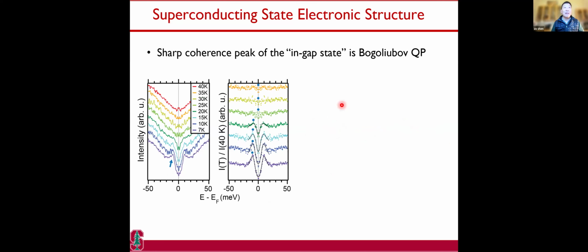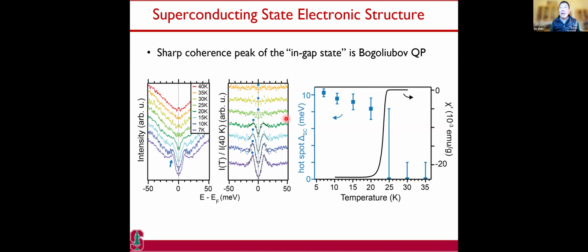Now we can do the detailed temperature dependence, and you can see that this quasi-particle peak disappears at the superconducting transition. So this in-gap state is not some impurity state of the bare sample. Actually, it is a state that gives rise to superconductivity. Okay. And you can see this gap turns on at the superconducting transition temperature.